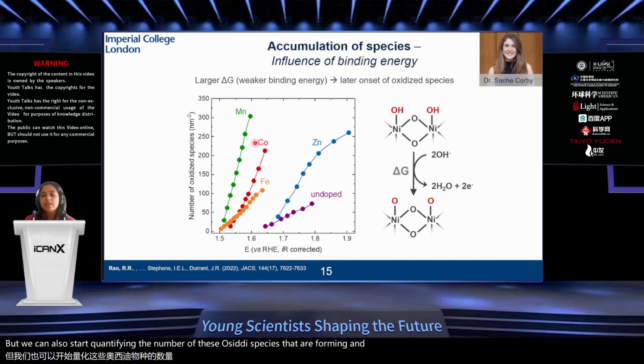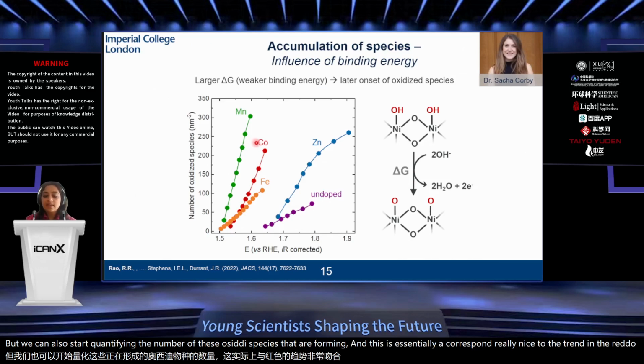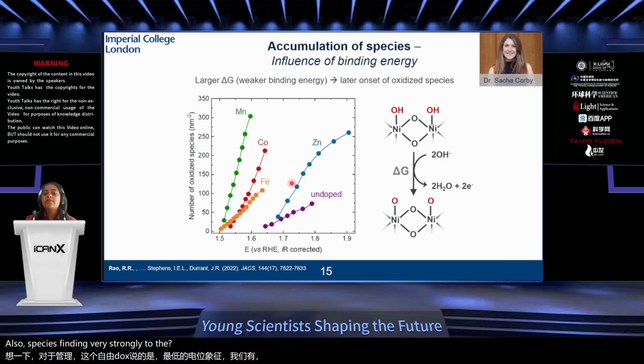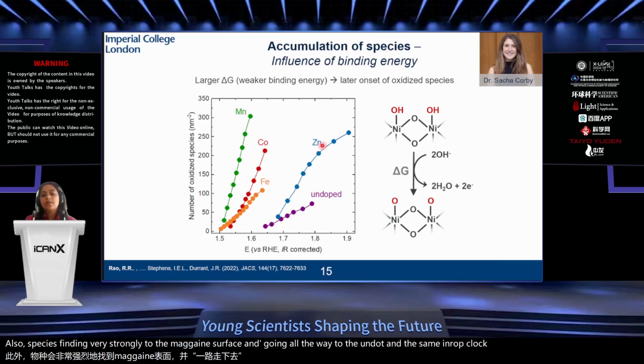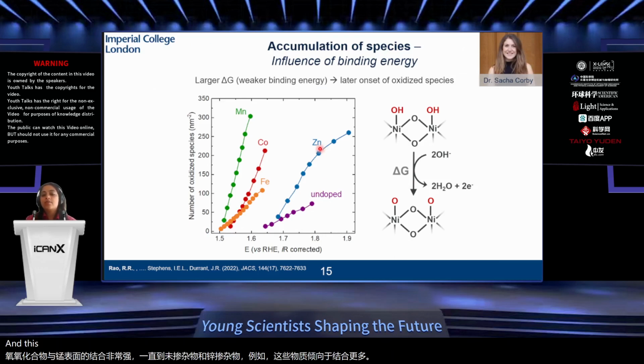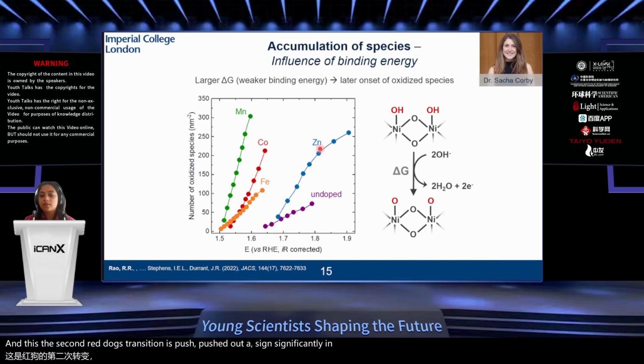And this essentially corresponds really nicely to the trends in the redox peaks that we were seeing, where for manganese, this redox peak was at the lowest potential, symbolizing that we have oxo species binding very strongly to the manganese surface, and going all the way to the undoped and the zinc-doped oxide, for example, where these species tend to bind more weakly, and this second redox transition is pushed out significantly into the water oxidation regime.